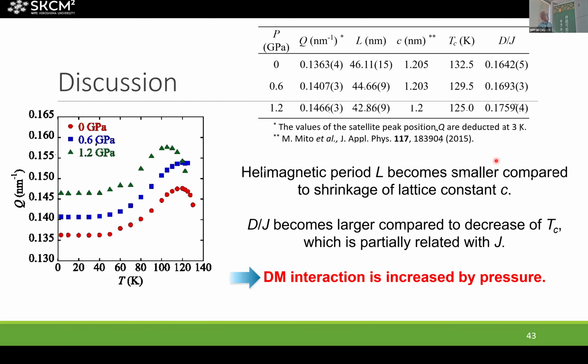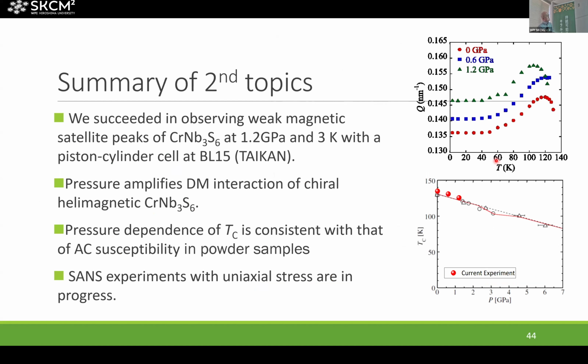And the Dzyaloshinskii-Moriya ratio D over J becomes larger compared with the decrease of transition temperature, which corresponds to the exchange interaction. From these results, we can say that the DM interaction is increased by pressure. But in this case, we cannot understand which is dominant, because pressure affects not only the DM interaction but also the exchange interaction. So we are trying to do uniaxial stress measurements to extract the effect of pressure on the DM interaction. We already did an experiment, and now data analysis is being performed by Kosaga-san.